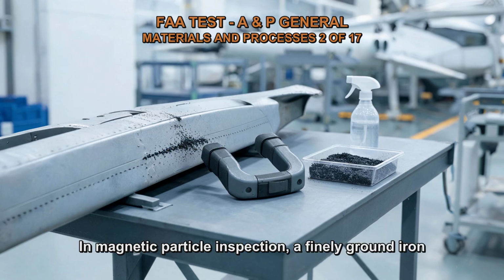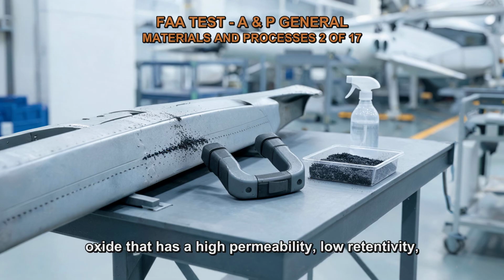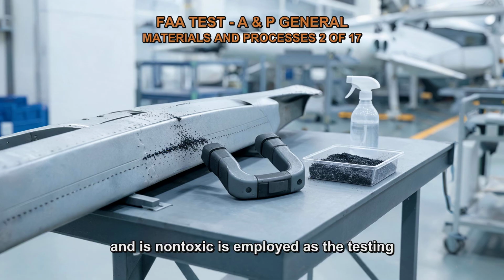In magnetic particle inspection, a finely ground iron oxide that has a high permeability, low retentivity, and is non-toxic is employed as the testing medium to show the presence of a flaw. It is typically suspended in a thin oil, like kerosene.